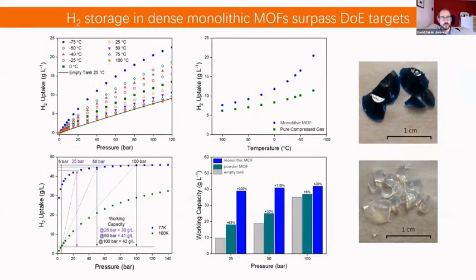We have done this for natural gas, but then we have also done it for hydrogen storage. Okay, this is a paper that is ready now to be submitted. This is basically the uptake of hydrogen that we can really reach. Okay, and this is something that we can measure at 77 Kelvin, and the comparison with an isotherm at 160 Kelvin. Okay, if we work at cryogenic conditions, at room temperature it doesn't work very well. But at cryogenic conditions, at 100 bar, we are able to reach a working capacity of 42 grams per liter and a total capacity of 48 grams per liter. Okay, so really, really high absorption capacities for these monolithic metal organic frameworks.